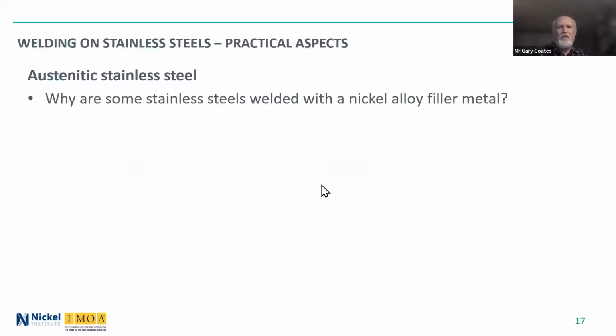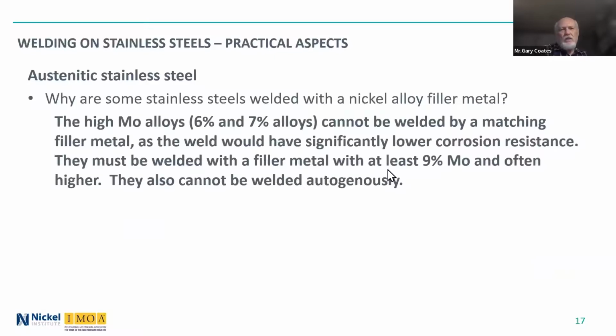And why are some stainless steels welded with nickel alloy filler metal? Well, the high molybdenum alloys, 6-7% molybdenum stainless steels, the 254 SMO, Al6XN, etc., cannot be welded with a matching filler metal, as the weld would have significantly lower corrosion resistance if it were done with a matching filler metal. So you have to use a very high molybdenum filler metal, the 9% molybdenum, which is the 625, or nickel chrome moly 3 electrode, which is most common for the 6% moly alloys. But the C family of alloys, Hastelloy C276, C22, and some of the other brand names there, can also be used, and they have even higher molybdenum content, anywhere between 11 and 16%. So they are more corrosion resistant than the base metal.